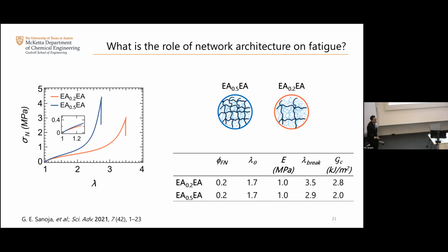It's not changing too much because, again, fatigue occurs here. Fatigue is a 10–20% deformation. So these systems have very, very similar elastic properties, but the strain hardening and the fracture energy are different. Okay, so we have a model system in which we have the same elasticity, but different properties at large strain. And what we wanted to understand is, if we have systems that have differences at large strain, how does that change the fatigue behavior, even if the elasticity is the same?